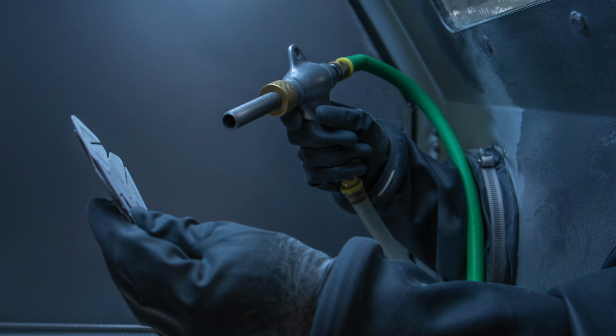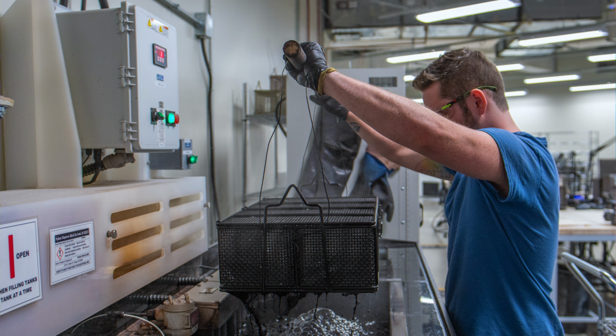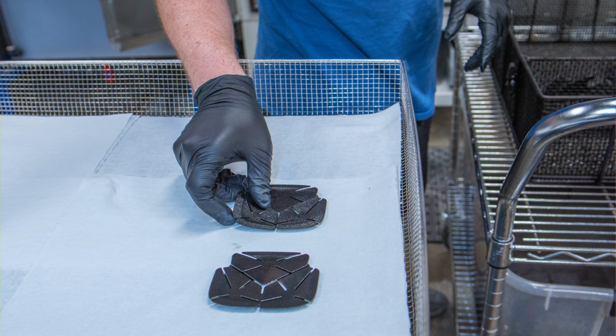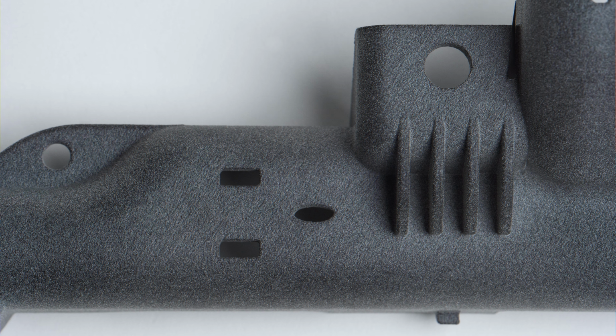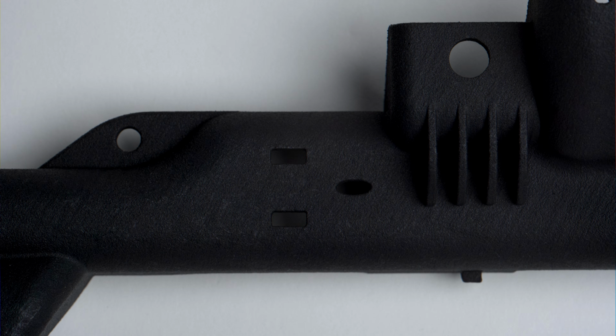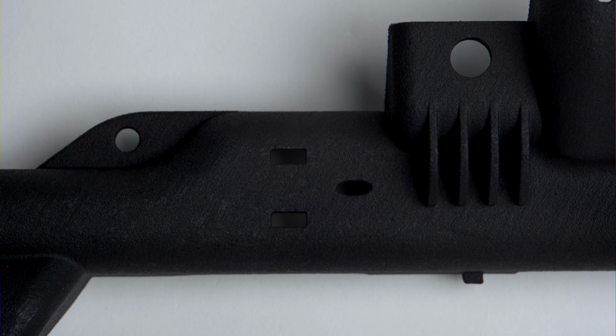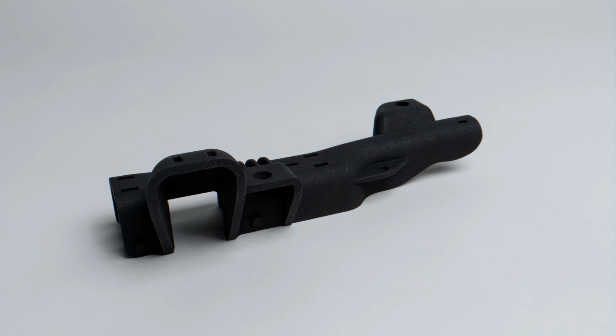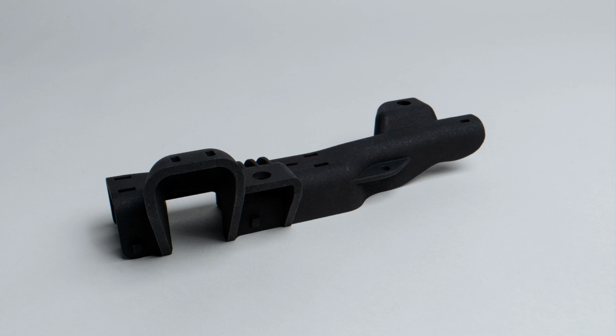Black dyeing is a post-process where parts are cleaned, optionally smoothed, and then immersed in a heated dye bath formulated for polyamides. The dye penetrates below the surface, typically a few tenths of a millimeter, depending on polymer, porosity, and process. So this is not just paint sitting on top. The advantage of this is if the parts get scratched, it doesn't show as much because the dye penetrated the surface. Thickness doesn't substantially change, so your tolerances are essentially preserved.